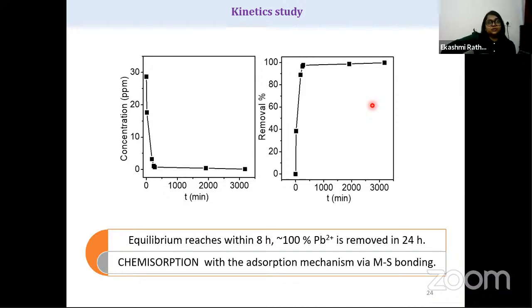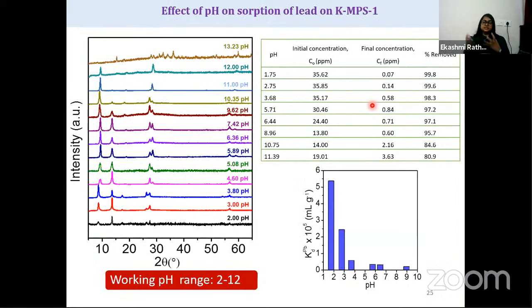Now let's have a look at what happens in different pH solutions. This material is highly stable, as indicated from the powder X-ray diffraction patterns. It's stable from 2 to 12 pH range, and we were able to remove more than 99% of lead. And here the values tell you that it's of the order of 10 power 5, which means that it's good in nature.